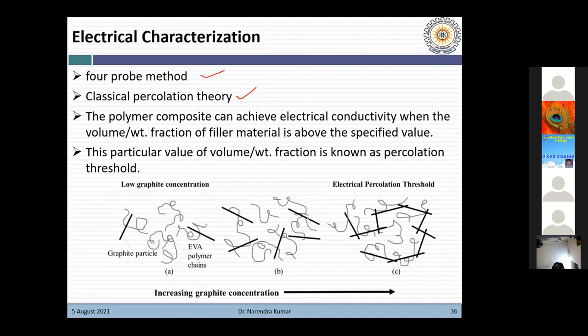So 1, 2, 3, 4. For example, here 5 graphite particles are there, but they are not making any network. But when we increase the amount, or the fraction of the filler material, then this kind of network is formed within the polymer matrix. So it makes this polymer matrix conductive, right?